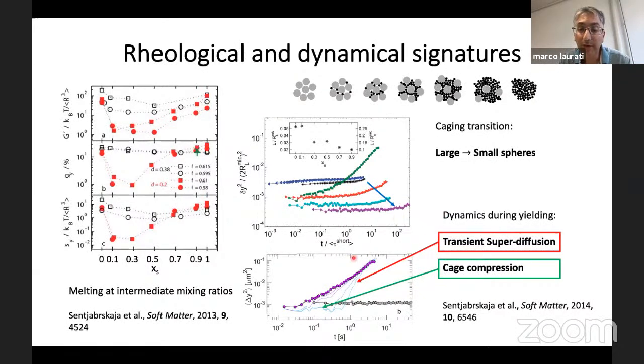So what we saw, interestingly, was that the system, from being arrested, was going to the flowing diffusive state through indeed a transient super diffusion. And also, there was an interesting effect that we could see: the equilibrium, let's say the steady state, localization of the system in the quiescent state was becoming smaller under shear, which indicates essentially a cage compression effect.